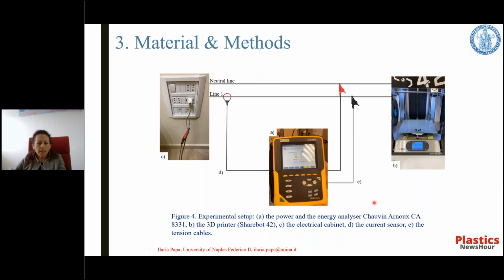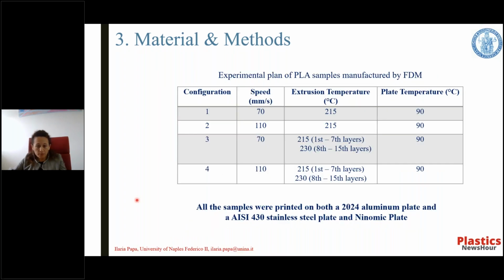And so in this slide, we can see the experimental plan of this part of the research. We fixed the plate temperature equal to 90 degrees to keep the material fluid and reduce the voids. That is a very common issue of this technology, as you know. We varied two levels of the extrusion temperature and also the speed, for a total of 4 configurations. So the speed is 70 and 110 millimeters per second. Also, 3 tensile specimens, as the standard suggests, were printed and tested for each configuration.